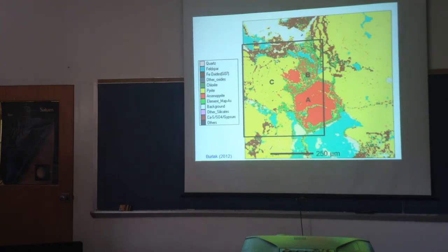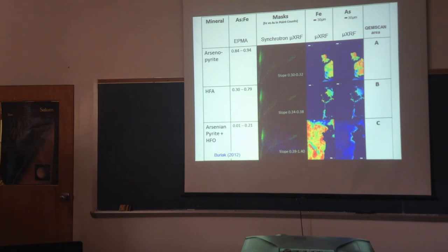Now this one, we took the additional step of taking the same polished section from the QEM scan and then taking it to the synchrotron, so we can learn about speciation and mineralogy from the same area. If you look at this rectangle, we've got these areas called A, B, and C. A is arsenopyrite, B is kind of a HFA type zone that has hydrous ferric arsenates, and C is a pyrite and very hydrous zone.